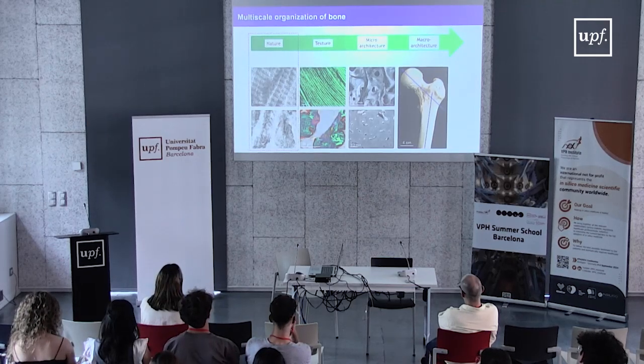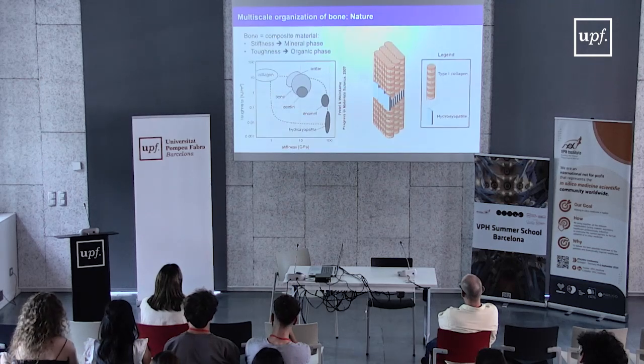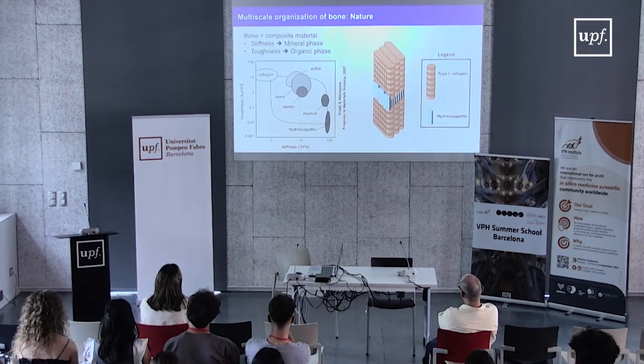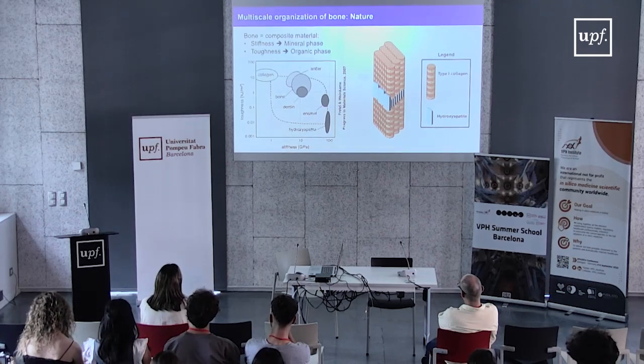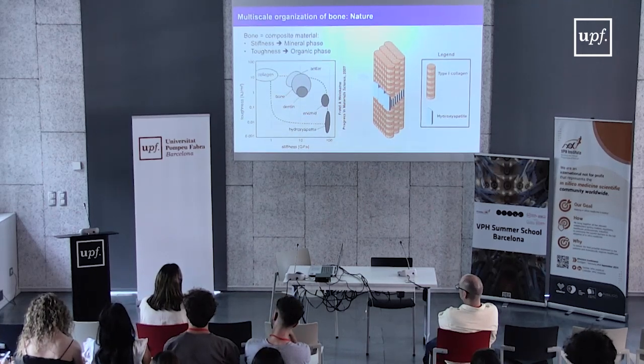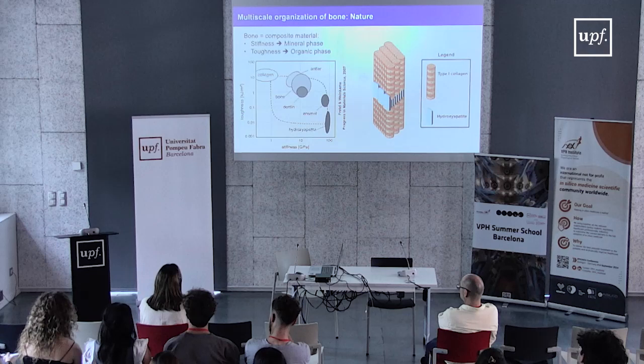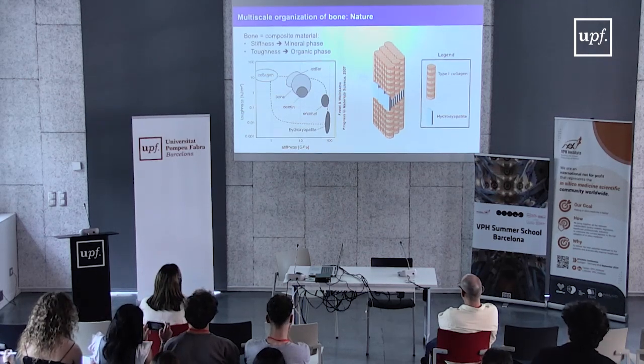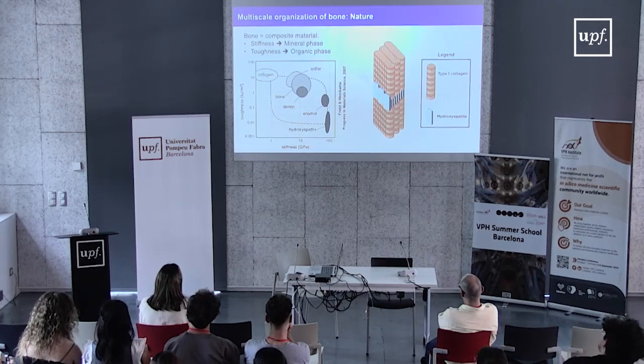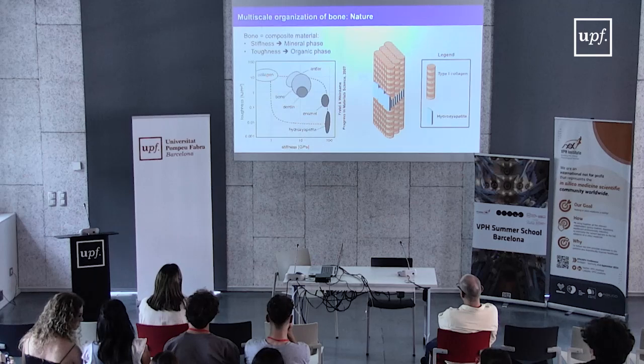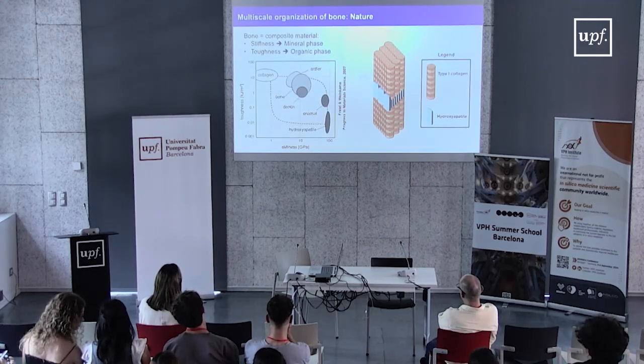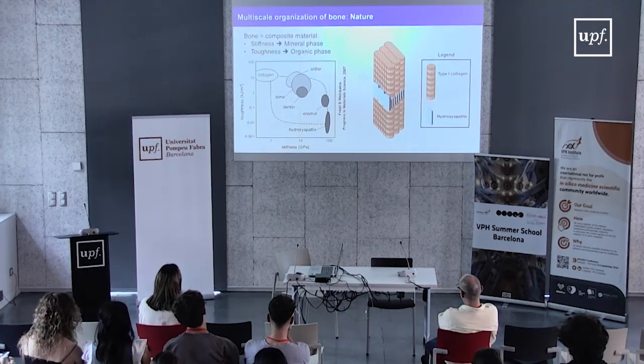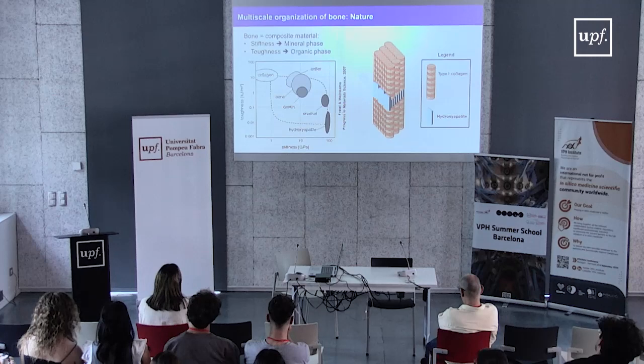So in terms of multi-scale organization, if we start with the nature of the bone, it is a composite material. You need to have a composite material to have all the mechanical properties to respond to the different stresses that apply. You need to have the calcium phosphate under the form of hydroxyapatite to have the higher stiffness which is required to sustain gravity. I'm standing in front of you. I have the gravity compressing my body. I need to have the hydroxyapatite and a good degree of mineralization of my bone tissue to resist to the gravity. And at the same time, you can see that hydroxyapatite has a poor toughness, and we need to have this composite with collagen to greatly enhance the toughness of the bone and the deformity without fracture of the bone. And this is brought by the collagen moiety. 90% of all protein are type 1 collagen.